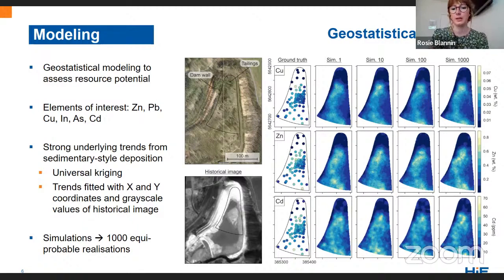So for example, in the figure on the right, you can see the ground truth, which is our geochemical data, and then examples of 4 simulations of copper, zinc, and cadmium. And you can see that they're all slightly different, but they're very similar, and they show the same trend of metal enrichment through the center of the dam and depletion around the dam walls. And this is what we would expect from the sedimentary style deposition.